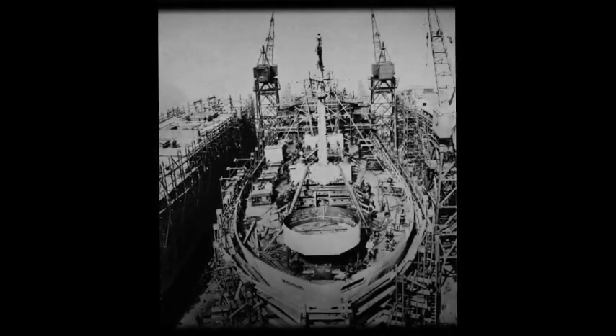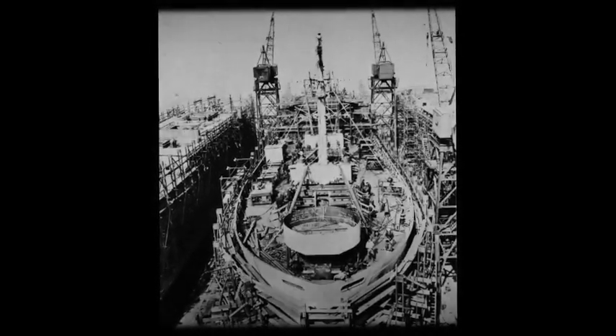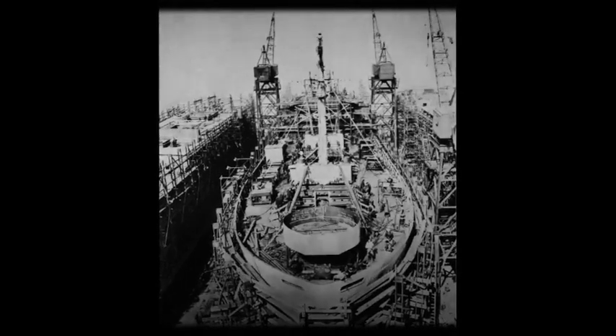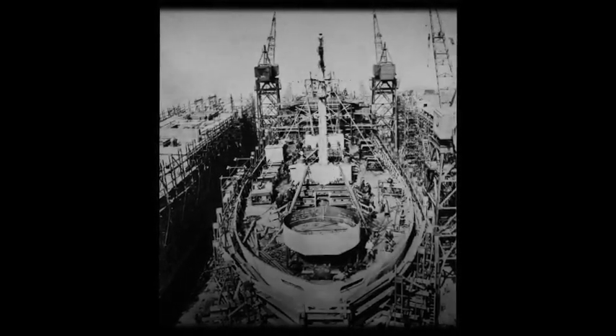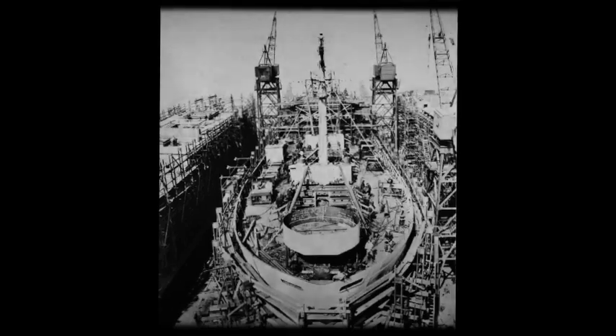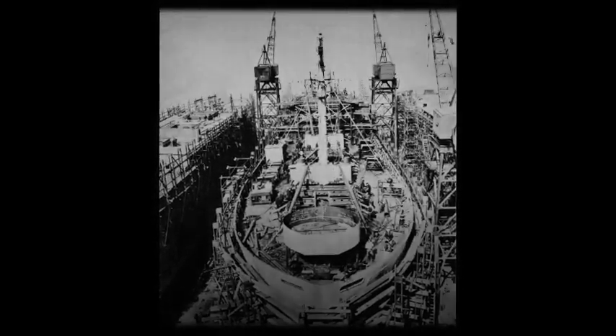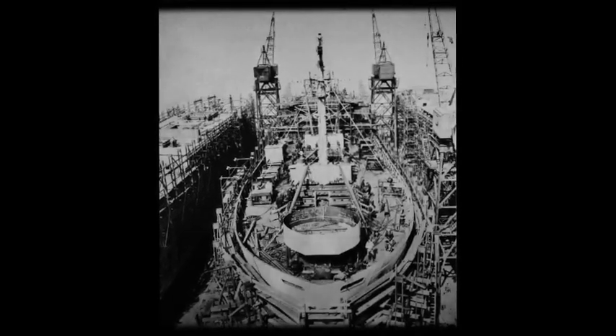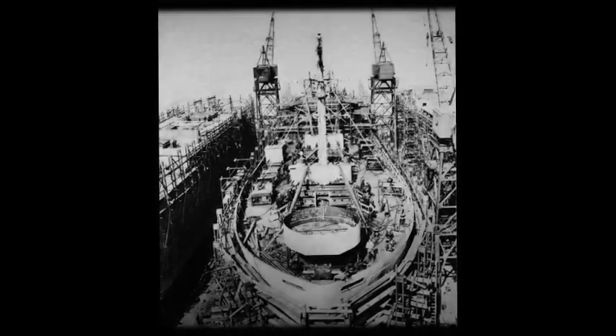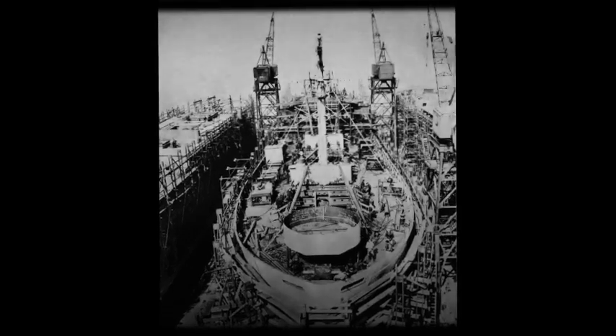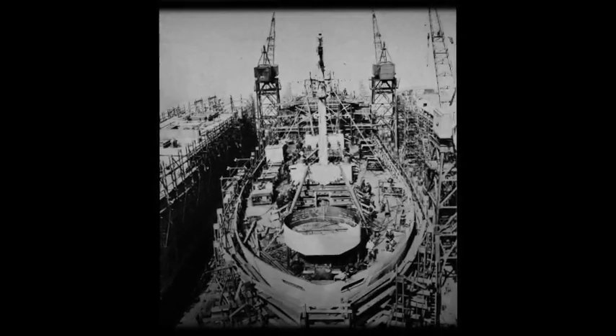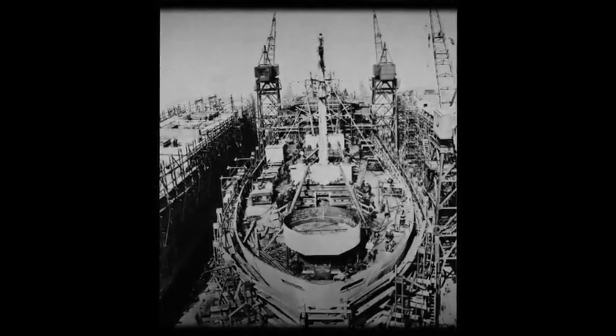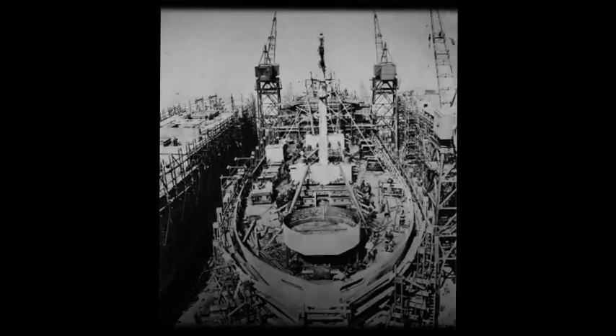Steel is not still or unchanging. It is a crystal-like material that reacts to heat and cold. When welders move a torch along a line, they make a super hot zone that can reach over 2,500 degrees Fahrenheit. The metal grows and expands in that heat. When it cools, it shrinks, but the colder steel around it keeps it from shrinking fully. This traps tight pulling stress inside the metal forever, unless the welding order lets that stress spread out slowly.